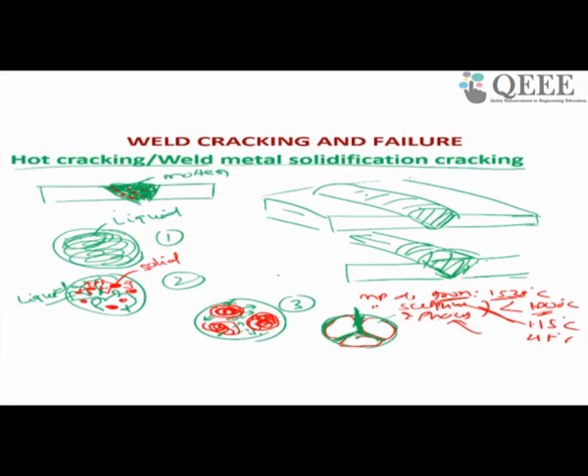So this will solidify and contract at a different level than this one. As a result, a tensile stress field will be created, and you will have a crack throughout. This is called a hot crack or solidification crack. You will get a crack throughout at the center.